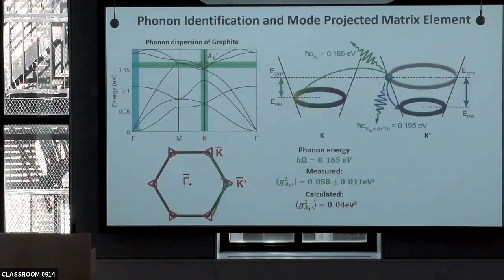Now going back to the question, John, you were asking. What do we know about this Q? Well, for one thing, we go to the phonon dispersion for graphite. We see that you have a mode at 165 meV phonon energy, and it is actually the optical mode at the K point, so this particular region. And then we ask, what is this connecting? Well, this is connecting two valleys of this material, from K to K prime.